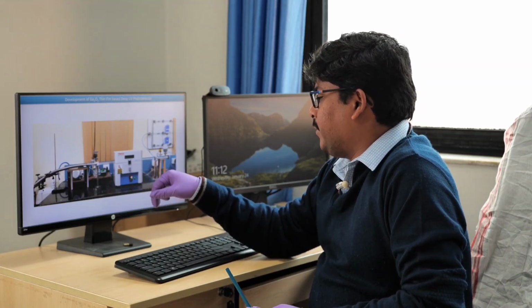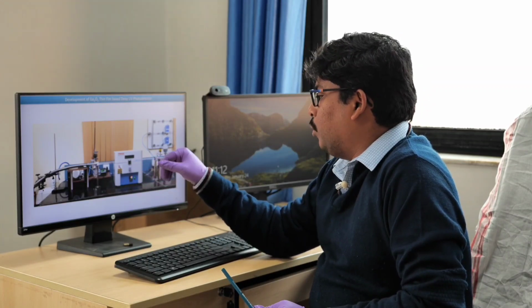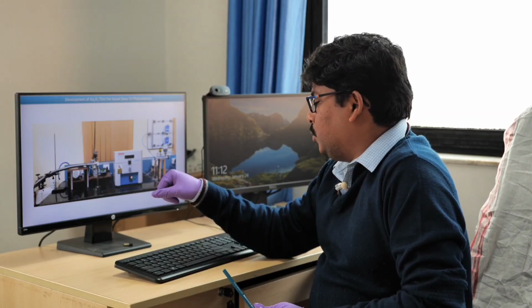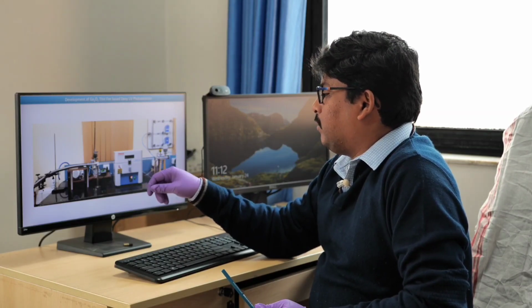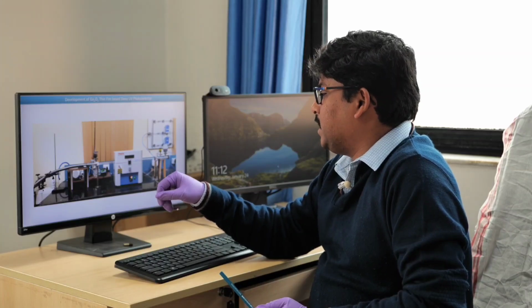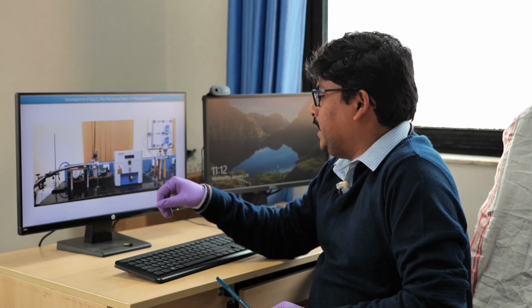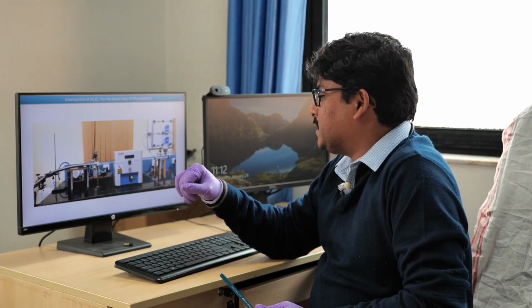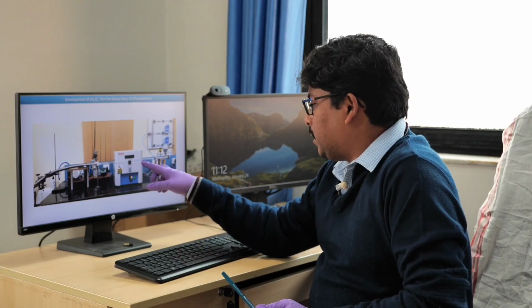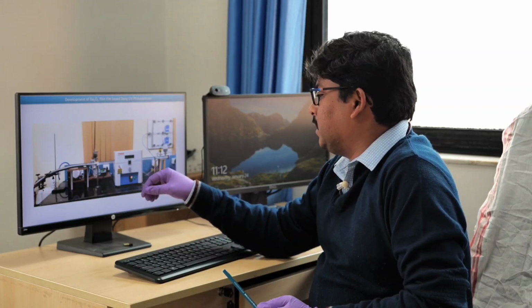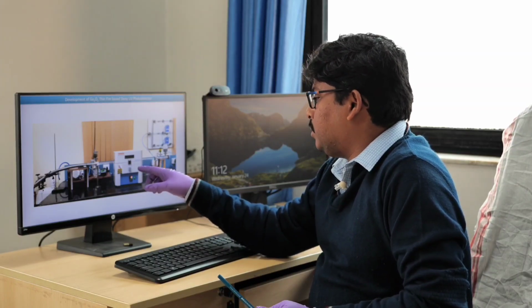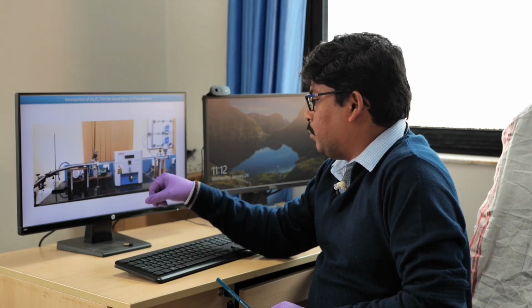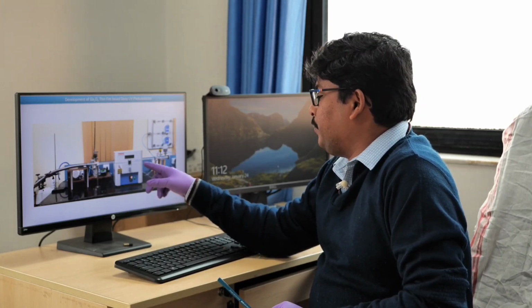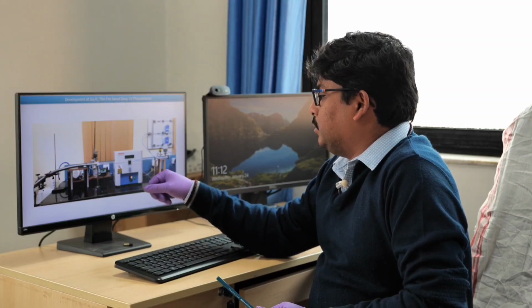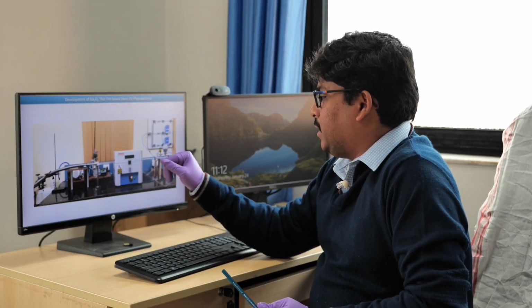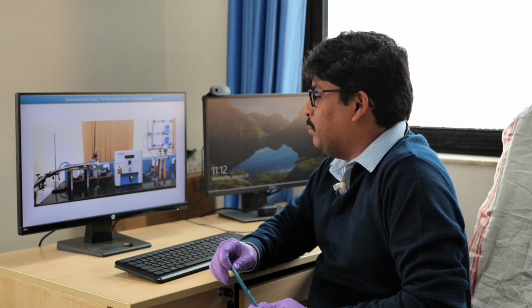After that we used another board where we kept the tin as a dopant, and as I mentioned earlier, initially it was very difficult to get tin incorporated in this gallium oxide material. But after a lot of trials and rigorous study, we could ensure that there is an incorporation inside this gallium oxide material as a dopant. So this is the setup that we used during that material development.